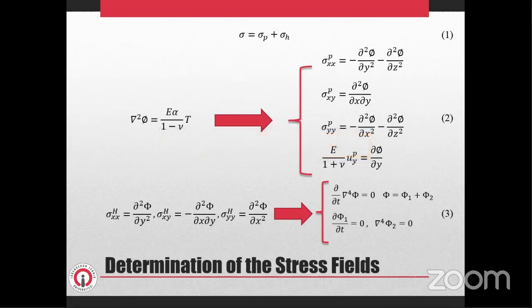Sigma P is a particular thermoelastic solution and symbolizes a determining solution depending on temperature distribution, and it does not satisfy the mechanical boundary conditions. Sigma H is the solution of the homogeneous problem without any thermal strains. The homogeneous solution allows us to satisfy the mechanical boundary conditions by providing an additional degree of freedom. A particular solution is determined based on the thermoelastic displacement potential, which is obtained depending on the temperature field by using this equation. The stress and displacement components can then be expressed using the following relations in equation 2.